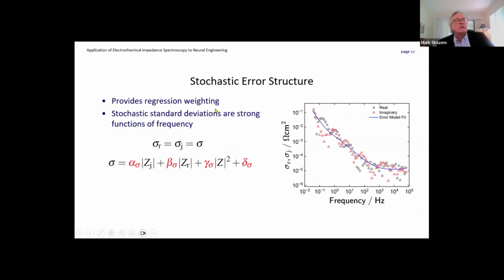When we use this measurement model and apply it to the replicate data, what we found is that this is the standard deviation of the measurement. The circles are the real part, the triangles are the imaginary part, and the blue line here is the fit of a model of this sort to our data. When I first started working on all this, I believed that the error structure was largely due to the potentiostat that you're using. But what I discovered in this work is that a common error structure could not be found. I have theories about this, and we can discuss it later.